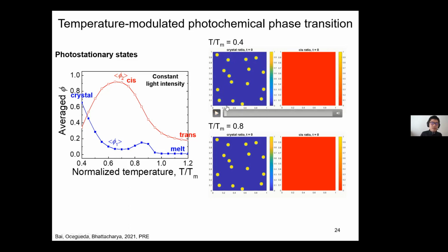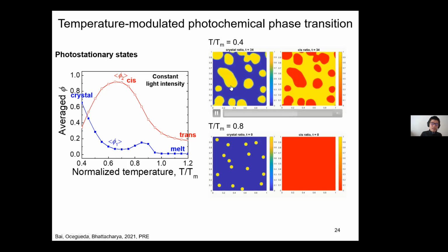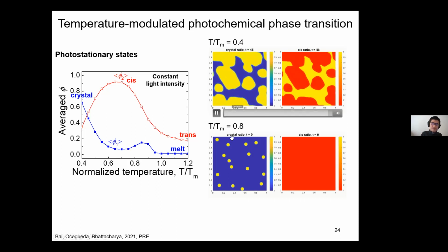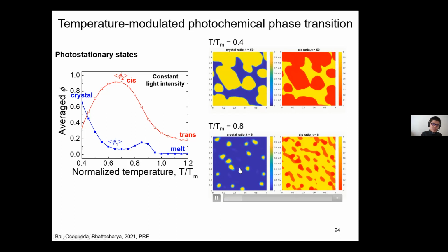So initially what we did here is we put some initial nuclei because we don't have a mechanism of generating nuclei. We don't have a statistical mechanism in this model. Now, when the temperature is low, in the end, you can see a large crystal domain here. But when the temperature is high, the crystalline domain doesn't grow too large. Okay, so this is just some simulation result we can enjoy.